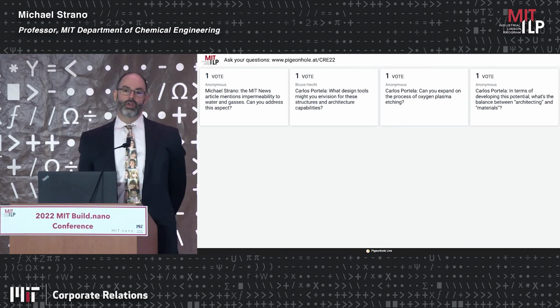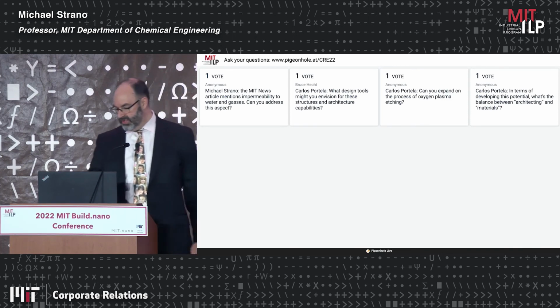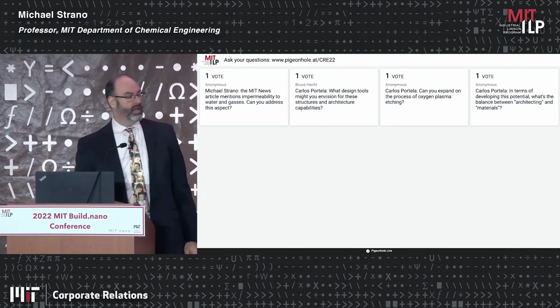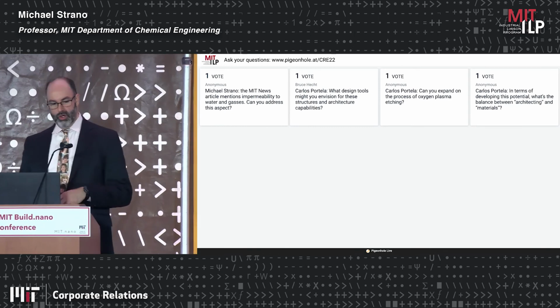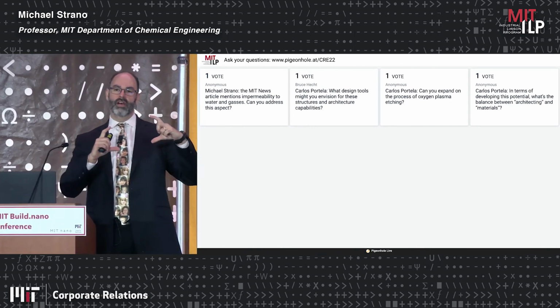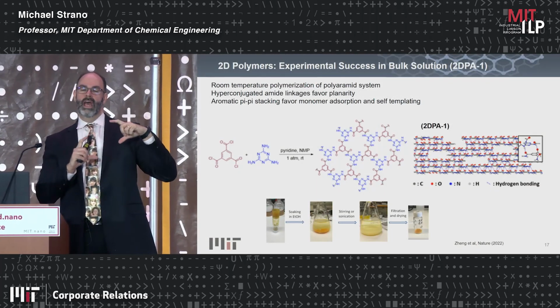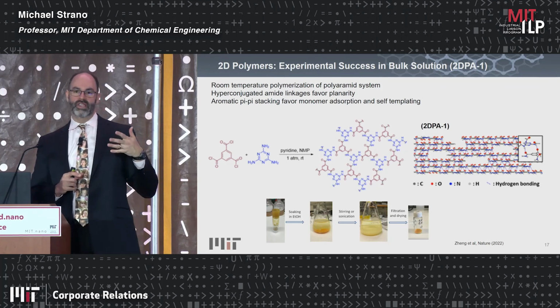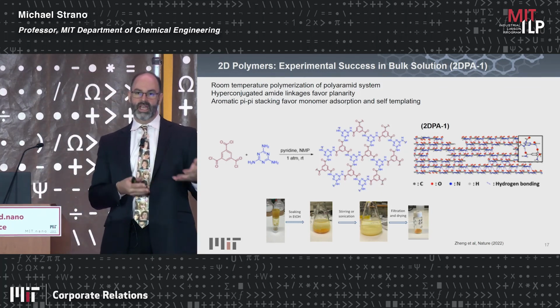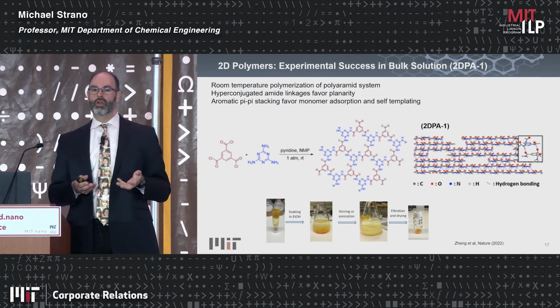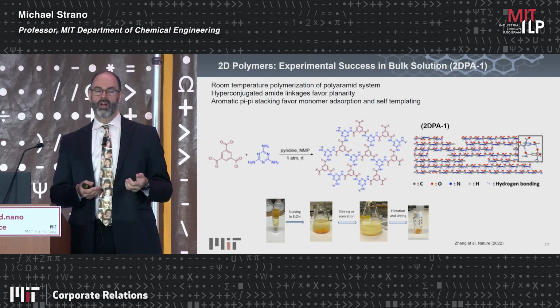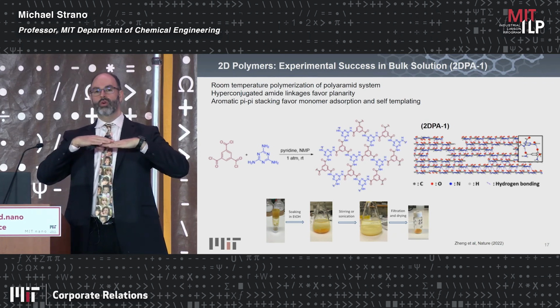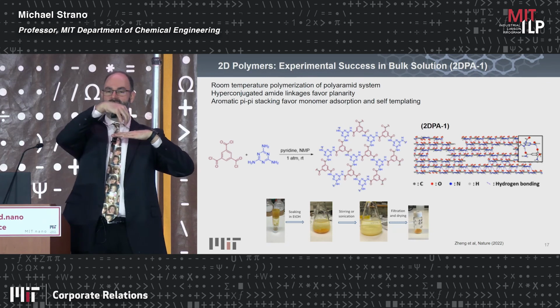Yes, we were surprised by that, because if you go into the unit cell, at first we were disappointed. Oh, we're not showing this. If you look at that unit cell, it has a large pore. And so when we measured the surface, when we measured the BET surface area, we were puzzled that we got no surface area at all. And so those pores were occluded. You can't get gas inside of them.